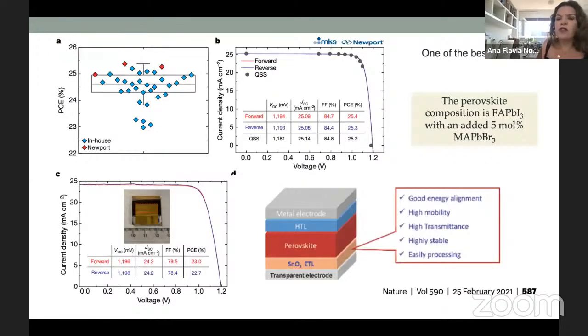One of the best solar cells is from my colleague Juan Pablo from Georgia Tech. As you can see here, he played with the chemistry of this tin oxide layer as electron transport layer. And they used this other composition for the perovskite, the FAPI, formamidinium lead iodide perovskite, and they achieved about 25% efficiency.